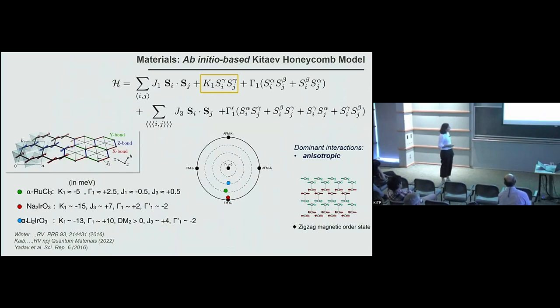So for alpha ruthenium trichloride, what one obtains, and in fact there are many other groups that are also doing ab initio, so the results are consistent between many groups, is that in this material there is an important Kitaev interaction, which is ferromagnetic. However, there is also a very important gamma contribution. So this is the other off-diagonal term that we have been seeing many discussions about in this conference, an important contribution that one needs to take into account to explain many of the properties of the system, as well as these two small Heisenberg interactions. And I have to say that this model, which is obtained from ab initio, we can explain thermodynamic experiments, magnetization experiments, torque experiments, as well as inelastic neutron scattering experiments. So this is a rather good model to describe the observations.